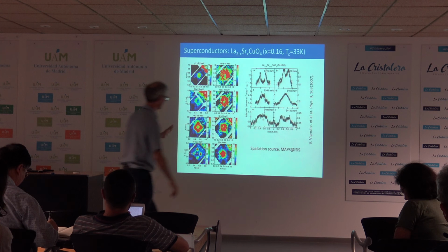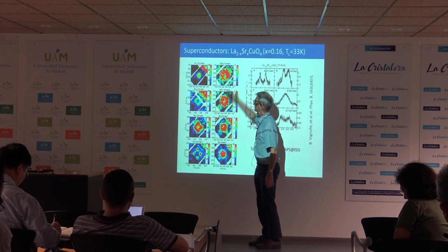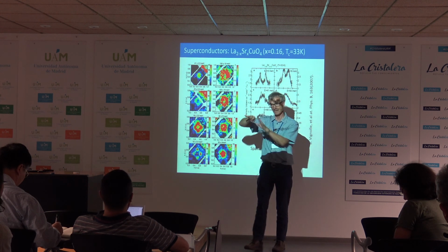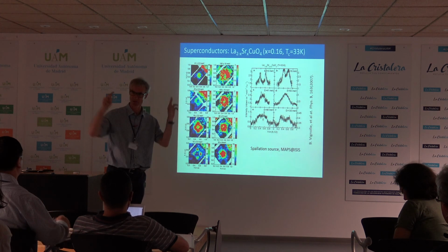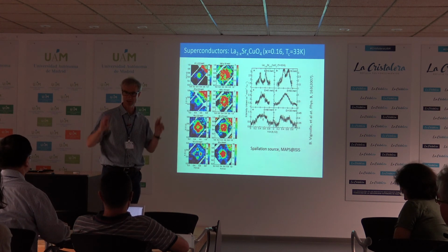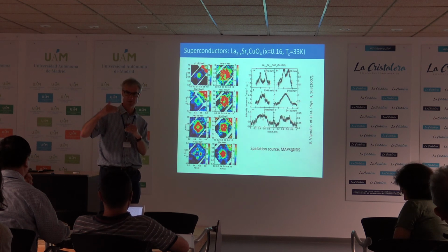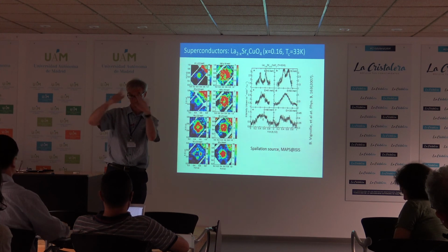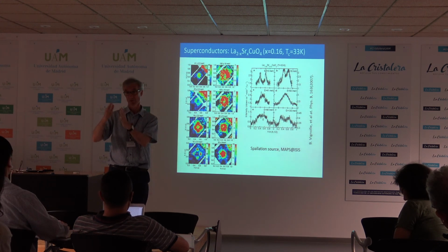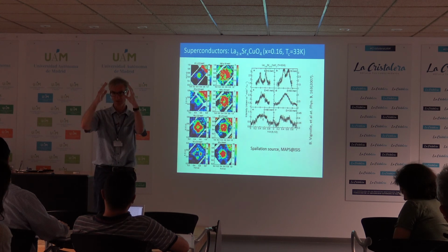So when you add up all these patterns over all energies, you see a broad peak at pi. And that's what those, in quotation marks, antiferromagnetic fluctuations are. Just as if you were to take an antiferromagnet and warm it up above its Néel temperature, you see the antiferromagnetic fluctuations. But the difference between that and what you see in high TC is that the stuff is much more structured.